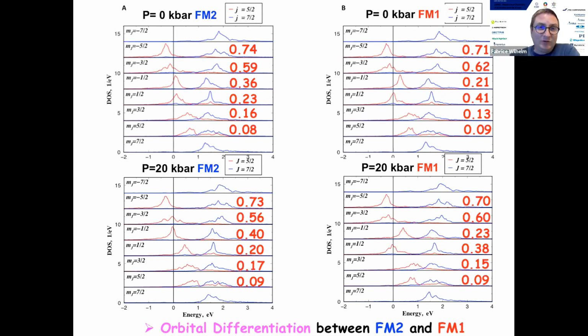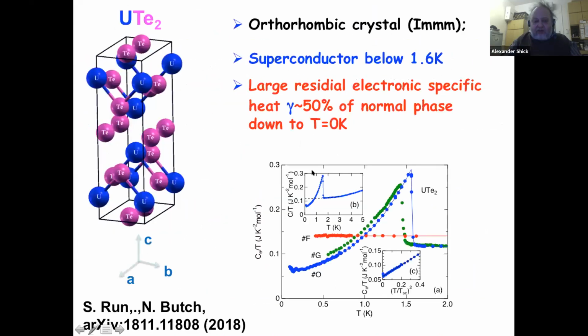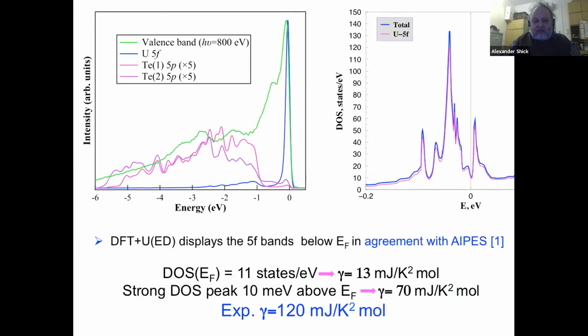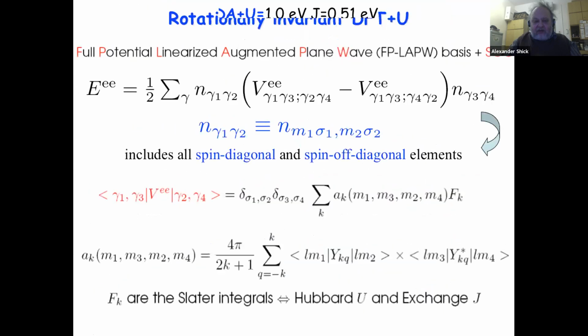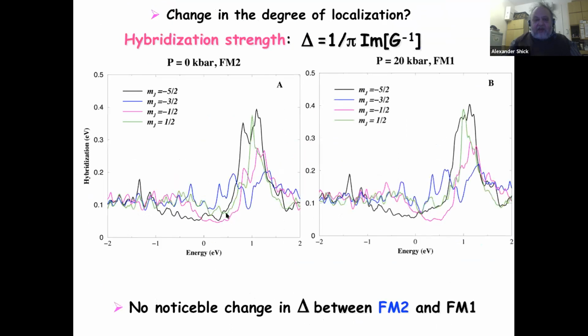Okay, because it is also said that under pressure you may change the hybridization a lot, and this may also give rise to changes. Actually, I can show you this. I was afraid that I would not have much time to talk about all the details, so I prepared some. Here are the hybridization functions in the FM2 at zero pressure and at FM1 at 20 kilobars. The hybridization function, as a function of the energy, measures the strength of the hybridization. There is not much change. They are not exactly equal, this to that, but there is no drastic change in them.